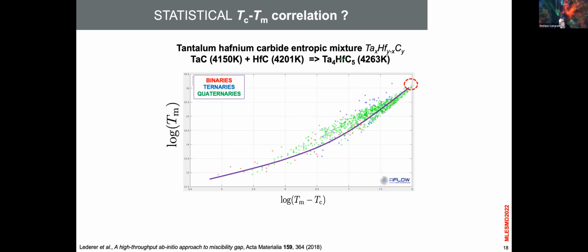And in fact, tantalum hafnium is a disordered solution because there is no order. So you have rock salt where carbon is in one position, and then tantalum and hafnium are mixed everywhere in a 4 to 1 concentration. All right. You can increase the entropy even further if you put in this mixture. Instead of tantalum 4, you put molybdenum, et cetera, and instead of having carbon, you put other species or vacancies. So that's the idea, to make high entropy, high melting point systems.